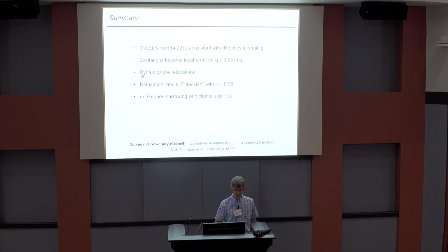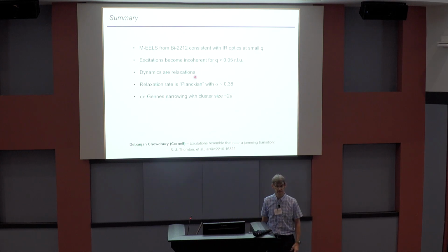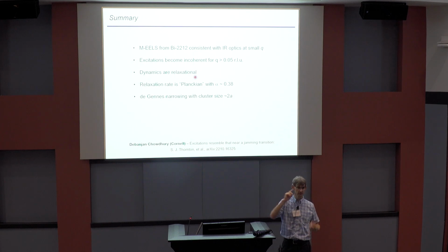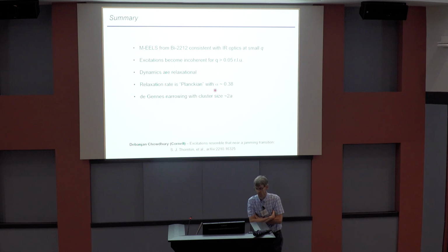And at low energy, the dynamics are relaxational. Relaxational means they fit perfectly to the equation you can pull out of Chaikin's book in the chapter on relaxational dynamics. Relaxational means that it's either dissipation or diffusion, okay? So the dissipative part is Planckian. It is linear-ish in temperature with a slope that's of order 1. And the diffusive part has a minimum at finite Q, which is an effect called DeGennes narrowing, which means that diffusive dynamics are dominated by finite objects that are colliding off of one another and propagating in a diffusive way. And the size of these objects is temperature dependent. And don't ask me what they are because I don't know.